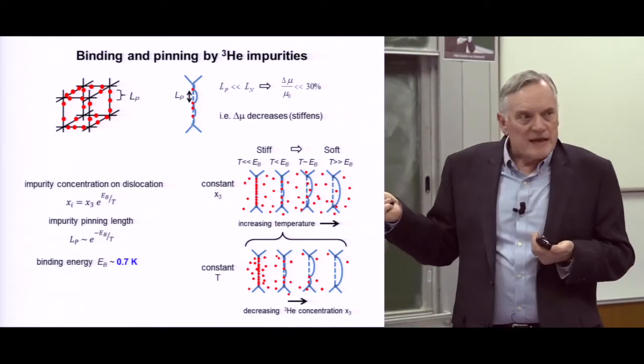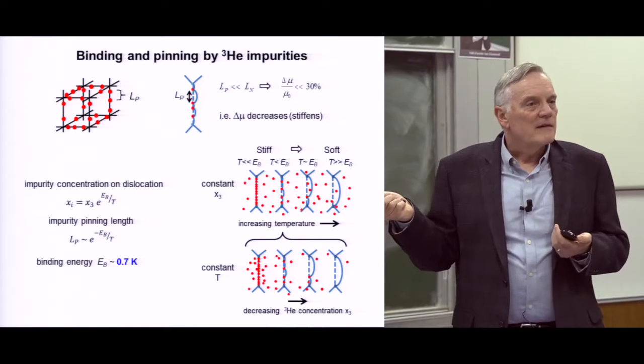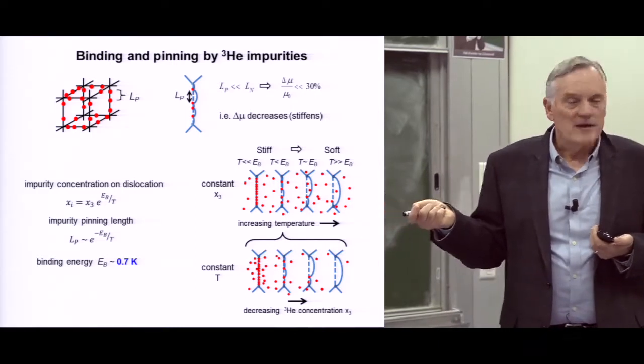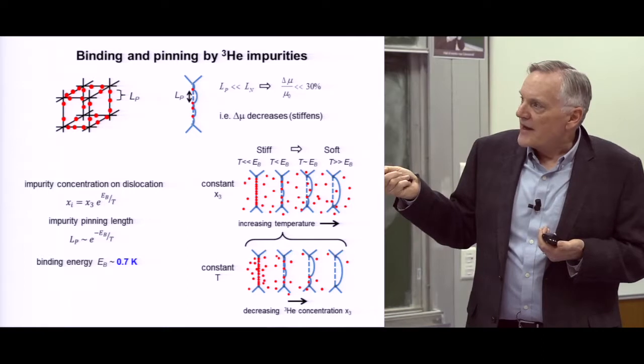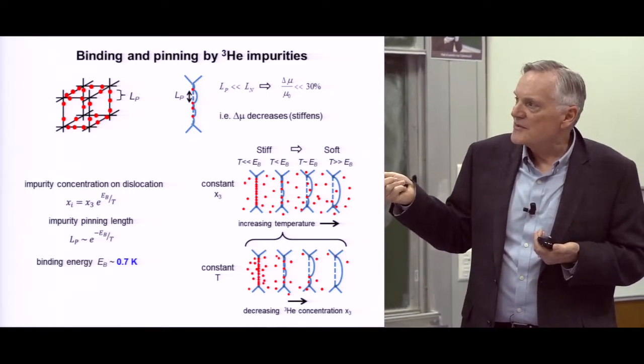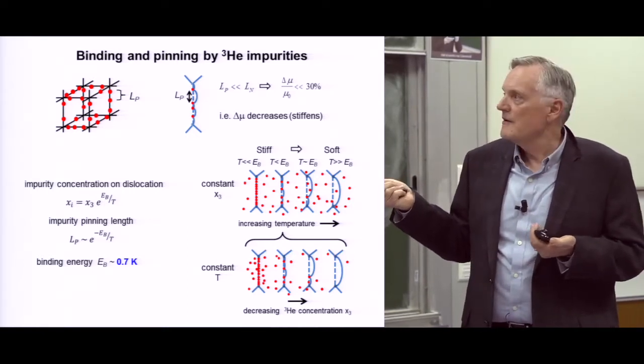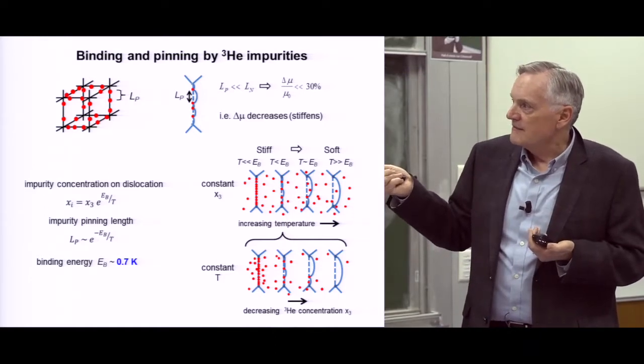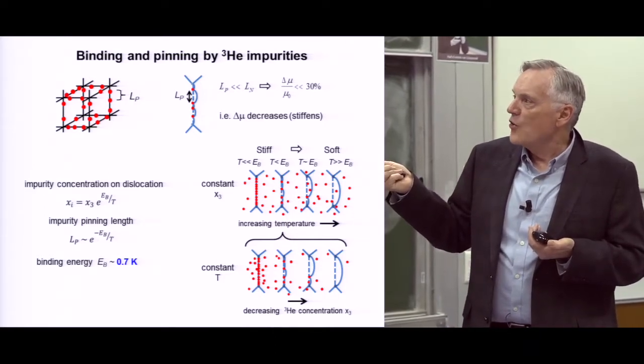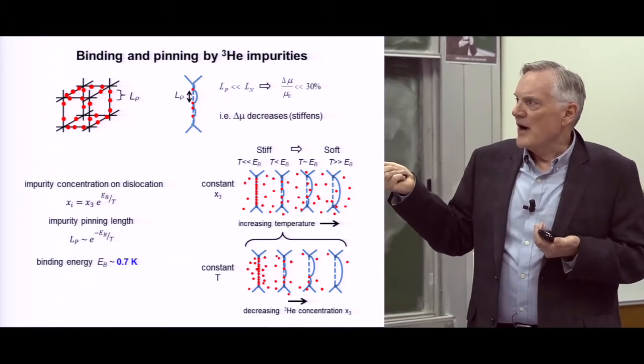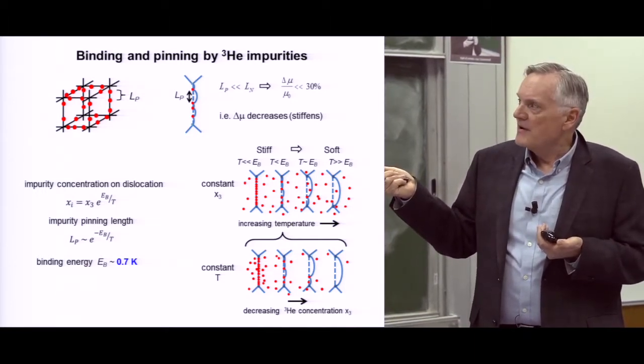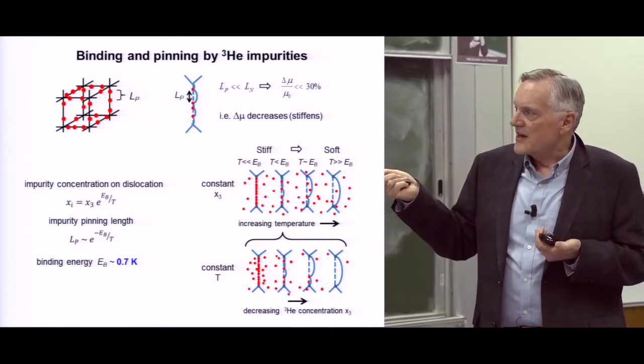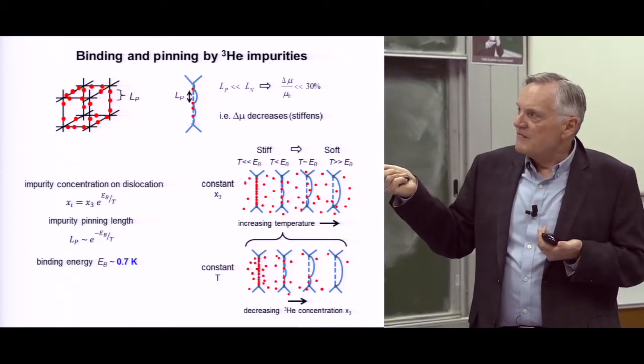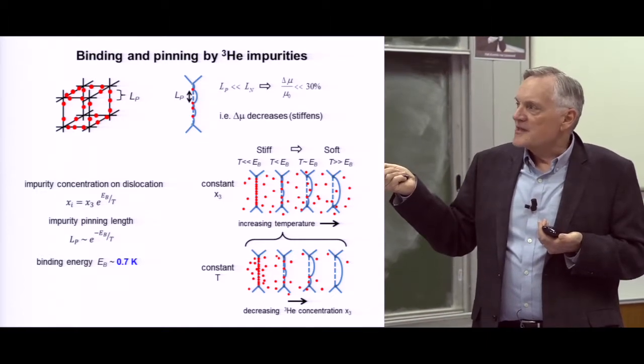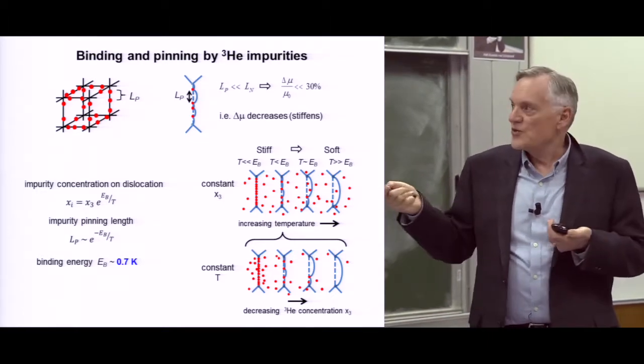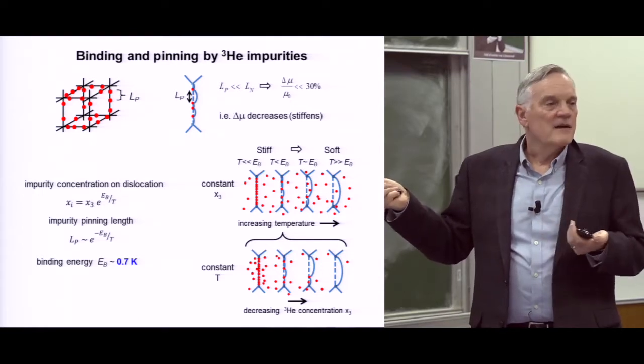And so this explains, in a sense, both the temperature dependence and the helium-3 dependence, because they're bound on. They have a binding energy. And so the separation between them is just e to the minus the binding energy over the temperature. And so if you think of this as a constant helium-3 concentration in the solid, and you're at very low temperature, they all bound onto it. It's completely immobilized. As you warm up, this changes just in equilibrium. And so the density of points becomes smaller, the length becomes longer, and they start to move. And so as you warm up, they unbind, and it becomes free to move again.